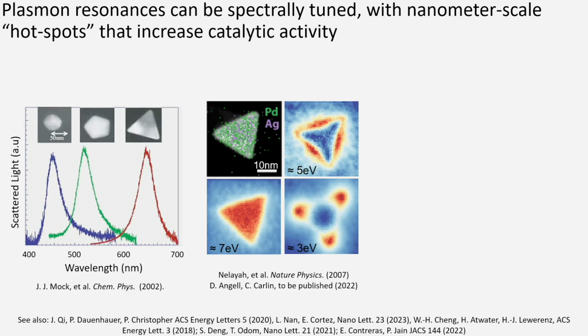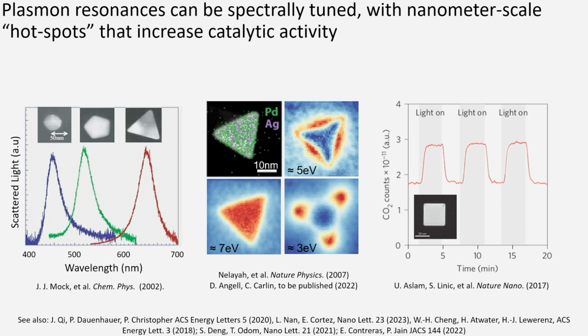But then if you look at how light gets concentrated at different wavelengths or at different energies, in this case 3 electron volts, 5 electron volts, and 7 electron volts, you can see that visible light gets concentrated either to the tips, if you're at lower energies like 3 electron volts, or to the edges if you're at 5 electron volts, or kind of all over the surface if you're at even higher energy, 7 electron volts. So these are experimental maps of how light is getting concentrated to deeply sub-wavelength scales on these nanoparticles. And then if you start seeing how these optically excited nanoparticles impact catalysis, like I mentioned, this is a pretty long and vibrant field, been around for at least 20 years at this point.